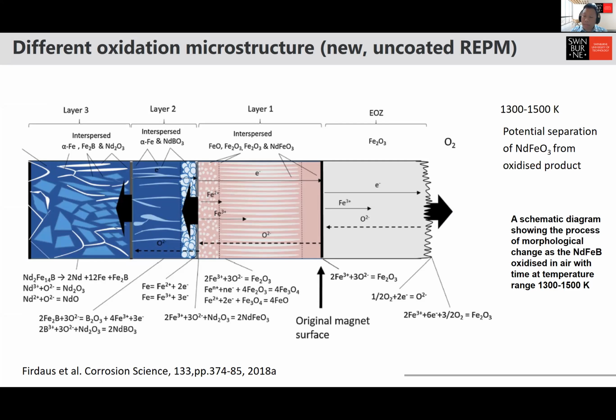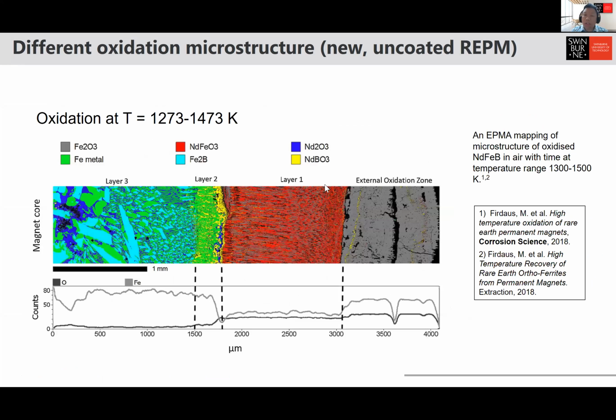In essence, I have a picture next one. Oh yeah, this one. So this is pretty good. This is oxidation at quite high temperature. So what happened is, as you oxidize, you started to form a thick layer of Fe2O3 on the surface, which is the gray one, the external oxidation zone. Now the gray one is quite easy to remove, because with just a slight tap of the surface, you can take it off easily. And then we have a layer where you mainly have concentrated NdFeO3. That's the phase that we want to extract, right? Interspersed with Fe2O3, right?